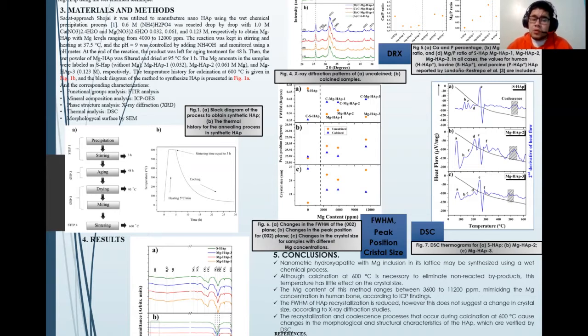The calcium nitrate precursor is added to the ammonium phosphate solution drop by drop. The reaction was kept stirring and heating at 37.5 degrees Celsius, and the pH equal to 9, controlled by adding ammonium hydroxide. This is monitored by a pH meter. After the reaction, the product was left for an aging treatment for 48 hours. This is because we need the crystals to grow.